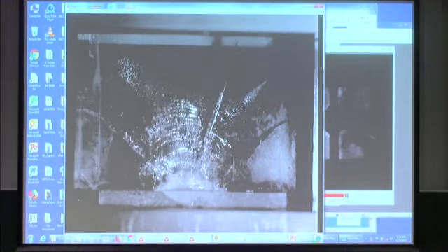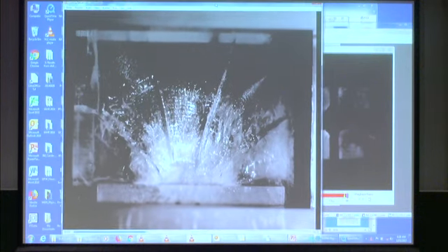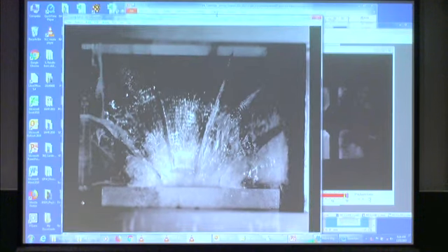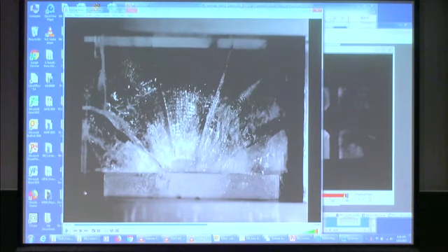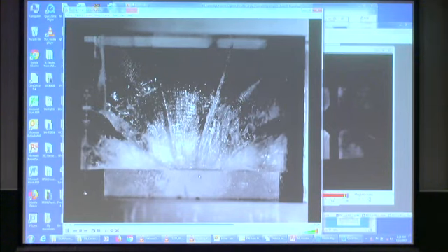So I wanted to point out a few important things here. So one thing is that the ice is staying intact. It's got some cracks in it, but the hard zone is actually here. And the slurry layer, you can actually see it here, and in fact we were able to get a thickness measurement from that. And you can see the slurry flowing out towards the viewer, and flowing down the front face of the platen.